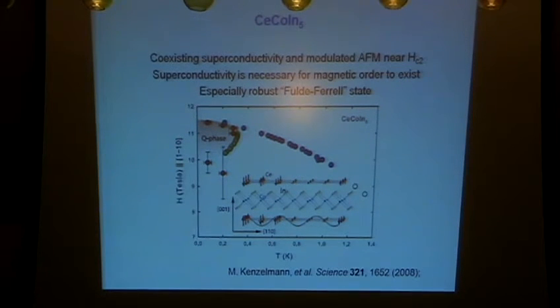In fact, in this phase, which is called Q phase, there is a spin density modulation, as well as being superconductive. Now, the odd thing about this is that this is not some boundary which extends out the other side. Up here, it seems to be a perfectly normal, or maybe not normal, but quantum critical system. This phase exists only inside the superconducting phase. And the magnetic order seems to be tied to it being superconducting very near Hc2.